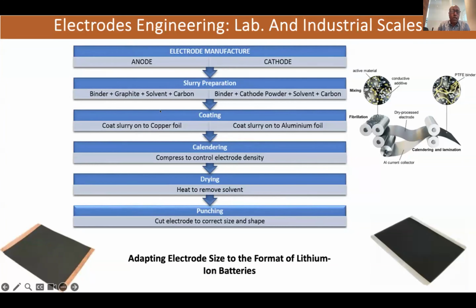And after that, we coat this mixture on the copper foil on the anode side, but on the cathode side, we have aluminum foil, using the roll-to-roll process. And then we have calendering. What calendering means is we should have a good contact between this slurry, this powder, and the current collector. That's why we put a press, we compress to control the density and also to control the contact. And after that, we have the drying process because we have solvent at the beginning. We should remove this solvent during the drying process,